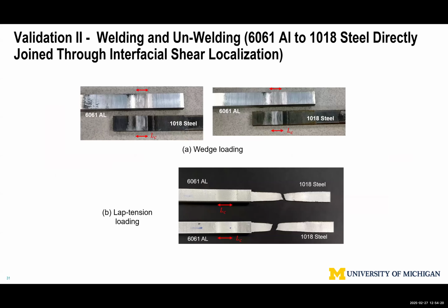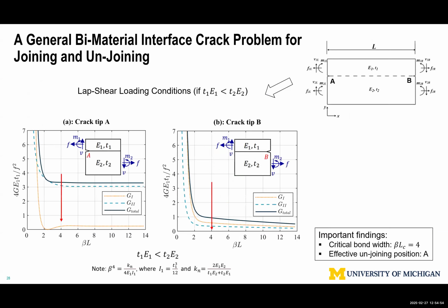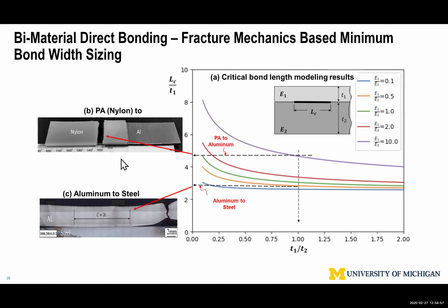Okay. So in that case, that means you want to have this type of failure mode demonstrated. That only requires that this bonding width has to be properly sized. Today, everything's empirical, just because the stress state is so complex, right? And also how to deal with defects. I'm not claiming we know everything, but I think this is a new concept we developed in the last couple of years. So that means if you want to have a clean open up, you have to have a trigger in the design. So that case gives you a clean interface. So coming back here, when you are the OEM or the regulator, you want to see this type of fracture under test, because that gives you the best load capacity, right? And today, we want to make sure this always happens.